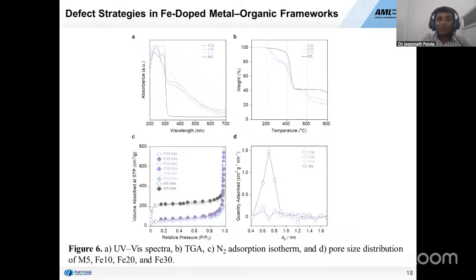Similarly, we have performed different spectroscopy techniques like UV-visible spectroscopy. This is the diffuse reflection spectra, solid state UV-visible spectra. You can find the peak in the UV-visible region for the M5. But when we introduce some metal ions, there is a peak in the visible region, at 400 to 500 nanometers. You can see here, this is due to the iron 2 plus present inside the framework.